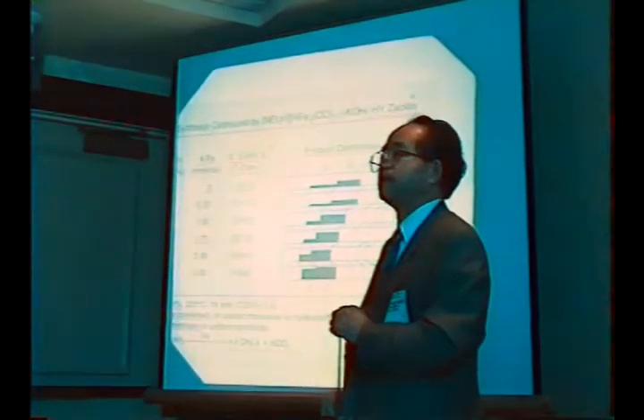Professor Zappa. Since you do have C4, C5, C6, one could perhaps judge the role of the acidity if you analyze the isonormal ratio. In a classical Fischer-Tropsch, you have only normal hydrocarbons, but when the acid function is still alive, we would expect under these conditions isomerization. So did you analyze the isonormal ratio of your higher hydrocarbons? I think this is normal. Yeah, only normal. So then there is no acid catalysis involved. I think. Thank you. And one last question.